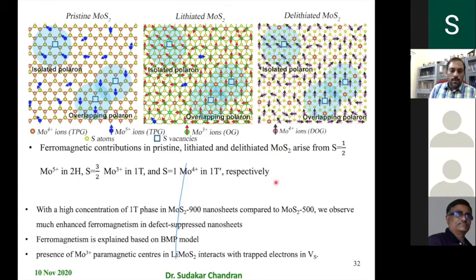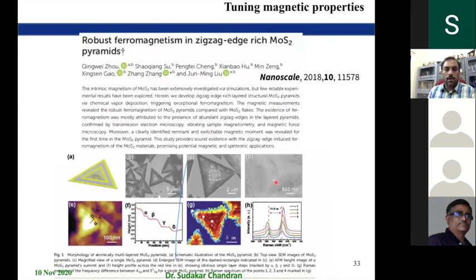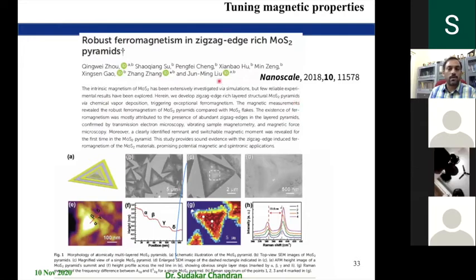So this is one of the interesting studies we found. Of course, you might see in the literature many such studies which try to understand the ferromagnetism. The recent one, some 2 years back. The one interesting one we found is they have grown these moly-disulfide triangular features, but then it is not monolayer. It is grown in such a way that it exhibits pyramids.